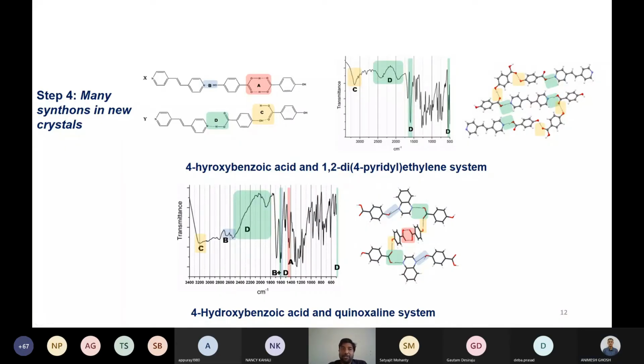So we tried to take 1,2-di(4-pyridyl)ethylene, and the 4-hydroxybenzoic acid, and we tried to analyze the IR spectra. We observed only C and D synthons, and that means that only this possibility is the reality. And then we tried to determine the single crystal structure. We observed the same structure there.